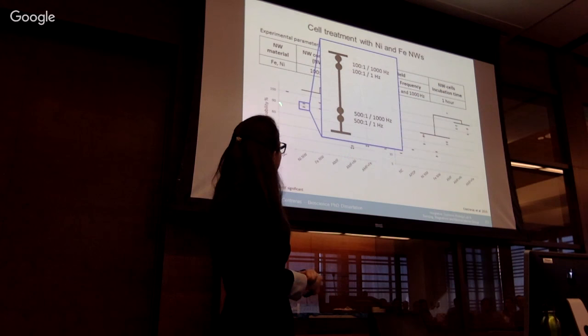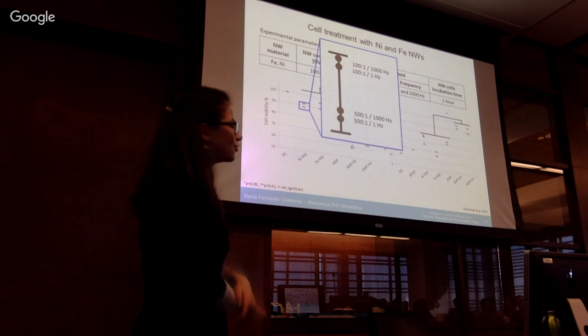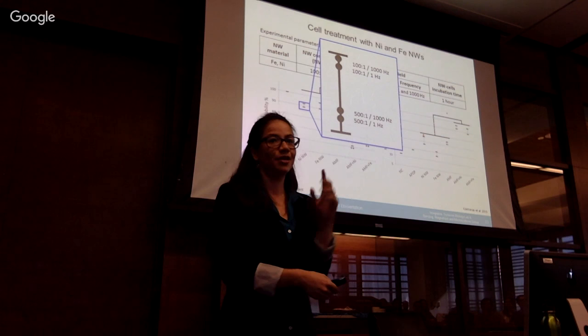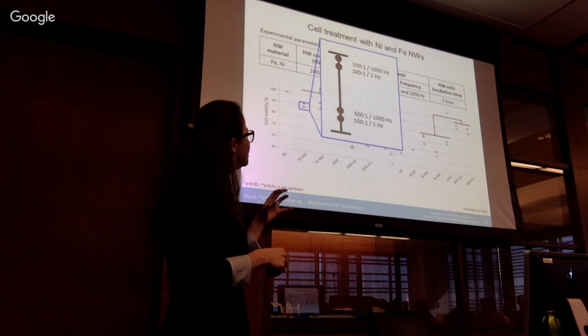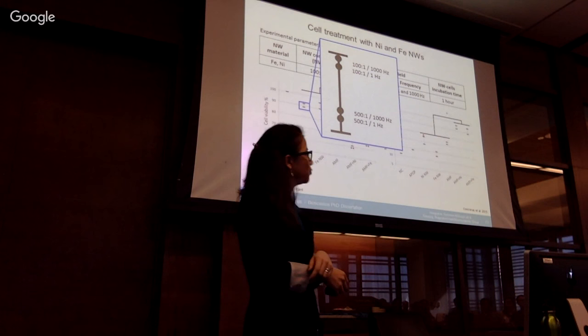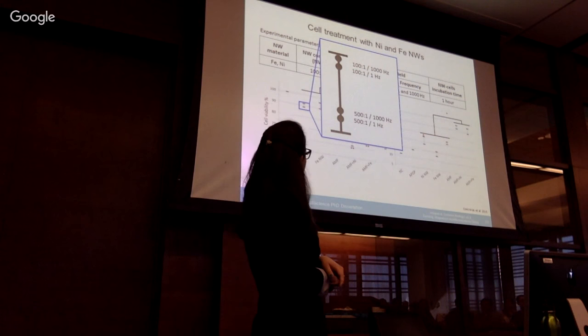Within this range, you do have, for example, your low concentration and the two frequencies used, and the same for the high concentration. These dots were drawn there on purpose because overall, I didn't see an effect of the frequency. So changing the frequency, changing how fast the wires rotate, didn't have much effect on the viability. The determinant parameter was the nanowire concentration. That made the viability drop more at a given condition.